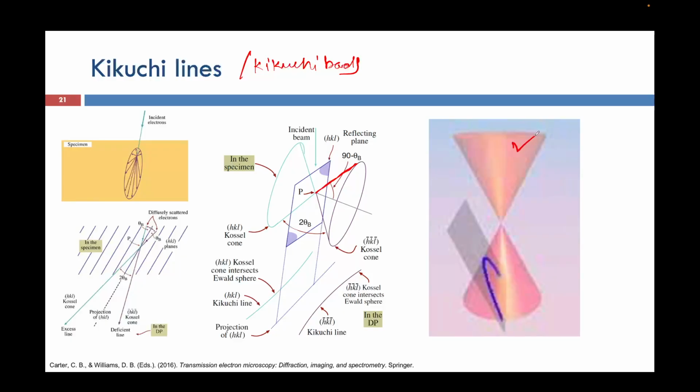So these are the two cones that I am talking about. That conical structure, the scattering will happen around in 3 dimensions. But when that conical structure gets intersected by an Ewald sphere, so here this is an Ewald sphere. Why have I taken a rectangle? Because the Ewald sphere is too large. So when the conical section gets intersected by an Ewald sphere, a parabola will form.